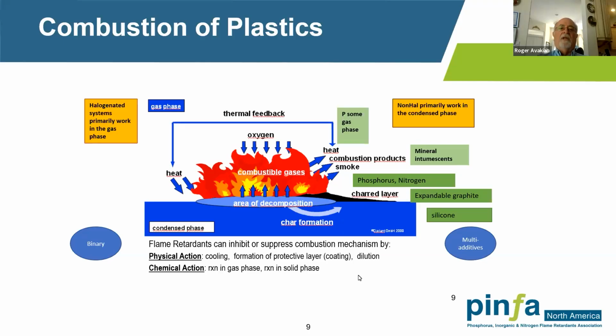Let's start with the halogenated flame retardants, typically using a synergist like antimony trioxide, although other metals can be used as well. But that's typically the synergist that's used with halogenated flame retardants. This combination of a halogenated flame retardant and, let's say, antimony produces free radicals that act in the gas phase to terminate the combustion reaction. So they're very effective and they work in the gas phase.